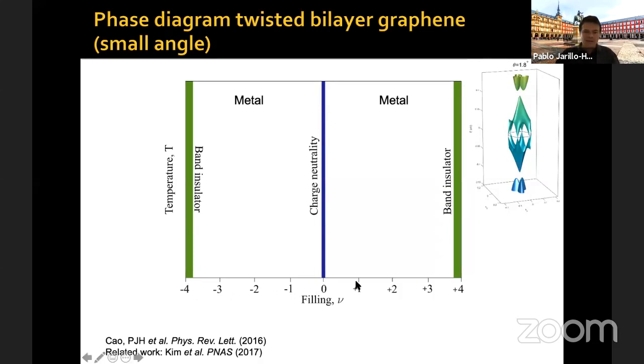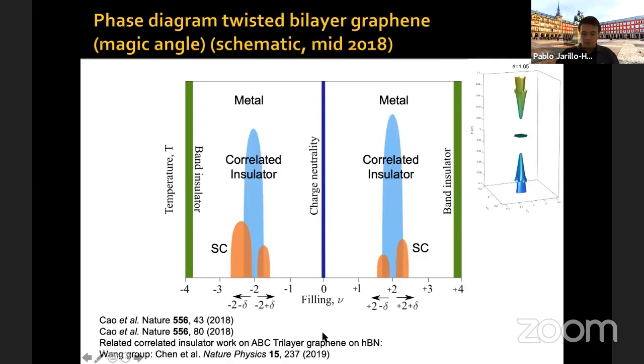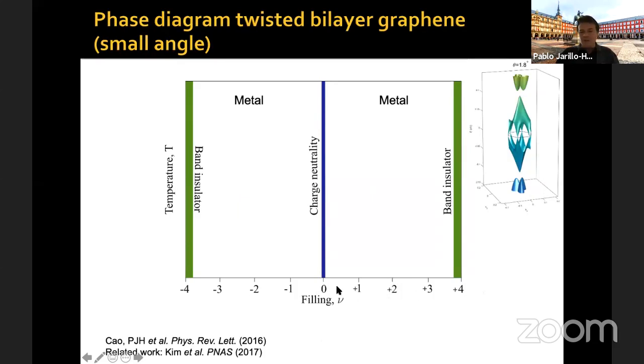And now, instead of density, I'm using filling factor, which is the density of electrons normalized by the moiré unit cell area. So this number 0, 1, 2, 3, 4, minus 1, minus 2, minus 3, minus 4 indicates 1, 2, 3, 4 electrons per moiré unit cell, or 1, 2, 3, 4 holes per moiré unit cell. And as I mentioned earlier, in these flat bands I can put up to 8 electrons, from bottom to top. So from charge neutrality, 4 electrons or 4 holes per moiré unit cell.